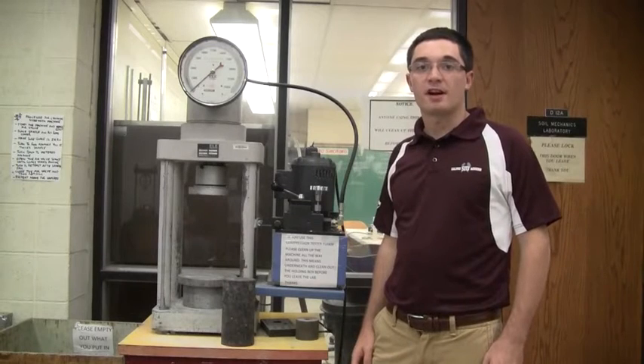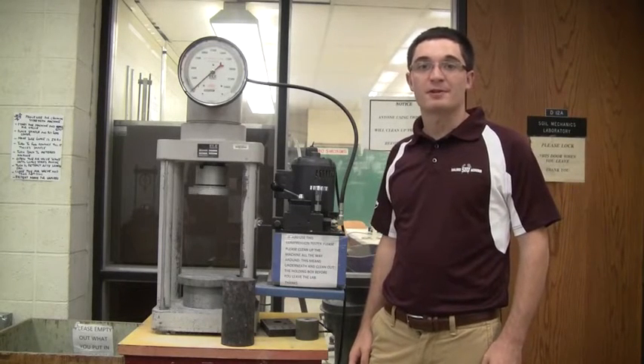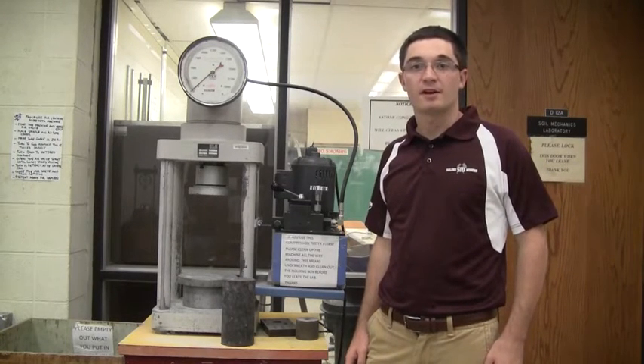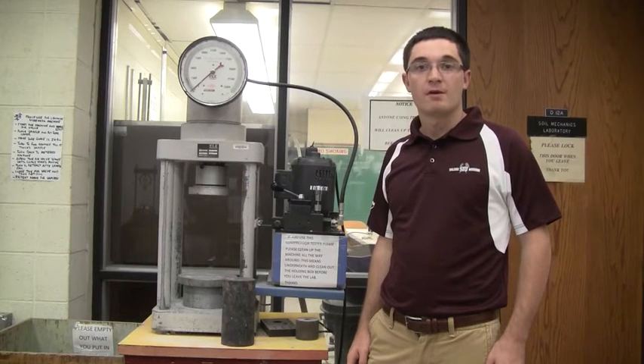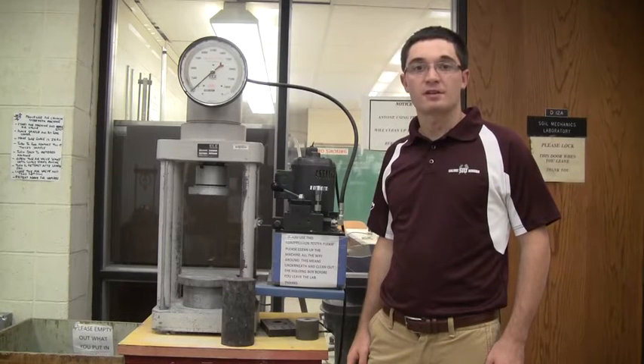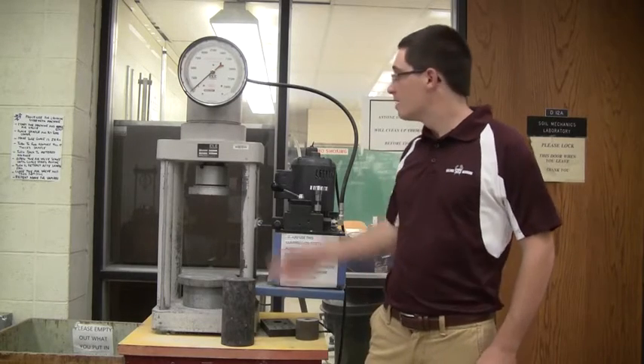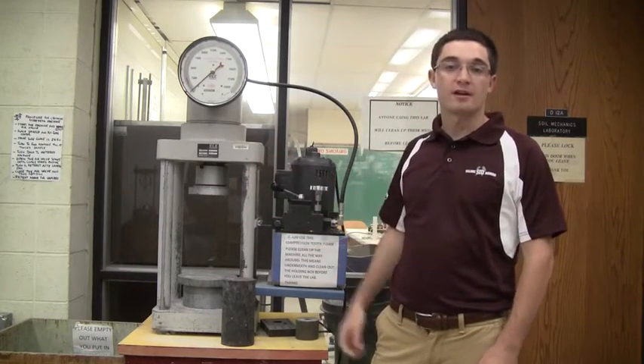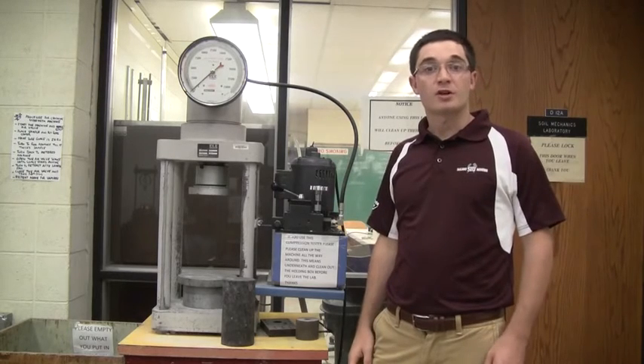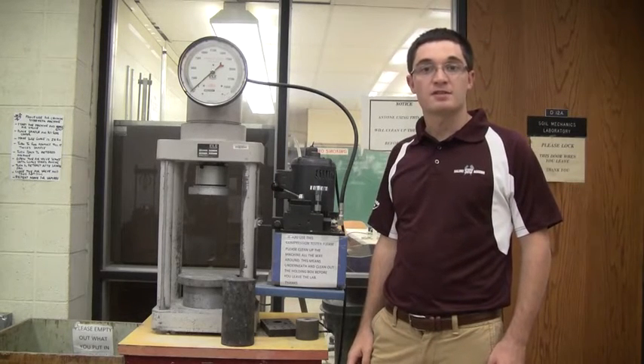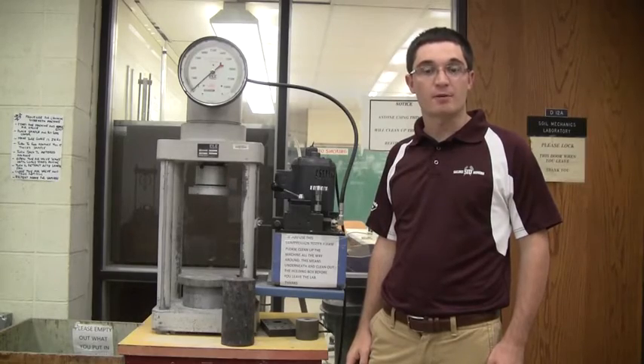Now that the cylindrical concrete samples have been rested for 7 days after curing, the compressive strength of the concrete can be tested for the first round. We monitor the strength variation in the early stage of the geopolymer concrete at day 7, day 28, and day 60. This is the machine that we do all of the concrete sample testing in. If long-term monitoring is needed, the sample can be stored for 1 to 2 years. In each test, 3 samples are compressed for a better representative strength.